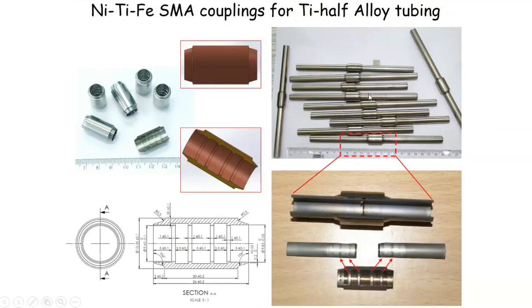So what is the way forward? One more thing which we believe could come is a hydraulic coupling. Now, there we were joining a PEEK insulator. Here we are taking titanium alloy tubings, which are used for hydraulics. You need to move the control surfaces for which you have hydraulic pressure. So if you join lengths, you conventionally do that with something which is swaged. That is a heavy piece, which you have to swage on the top externally with quite a major tool. And this has to have some swaging teeth on either side of the tube. It has to be swaged to lock on. So that's what is done.